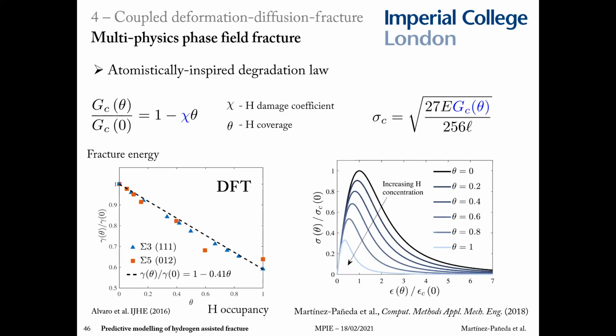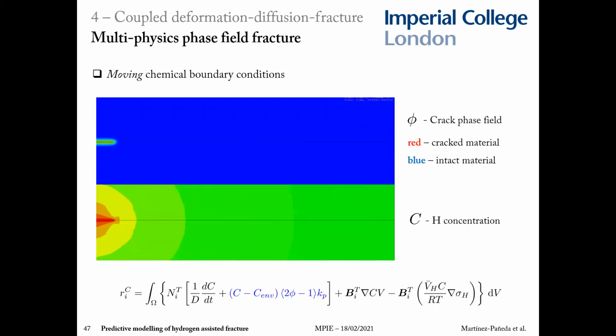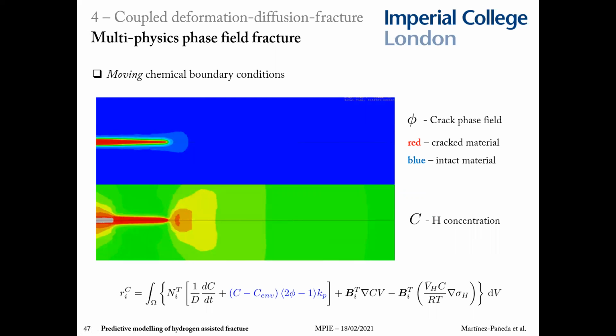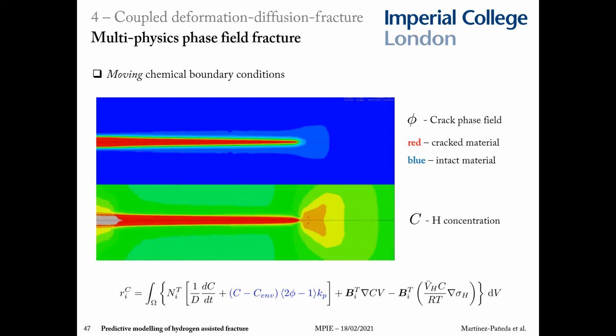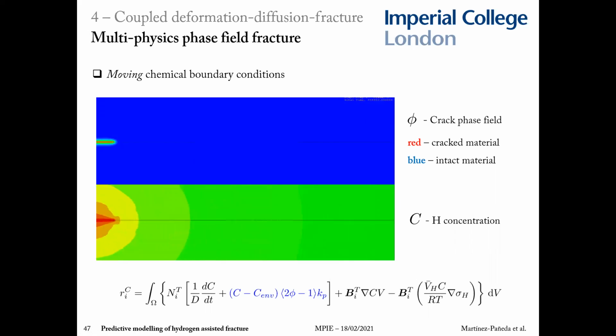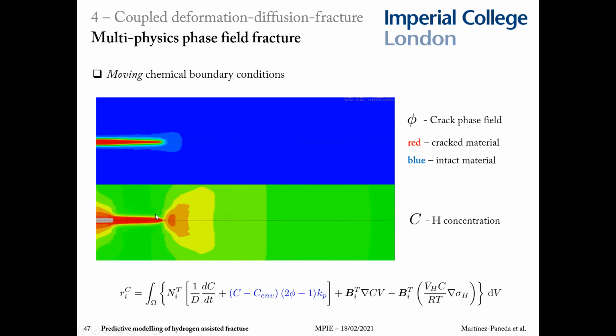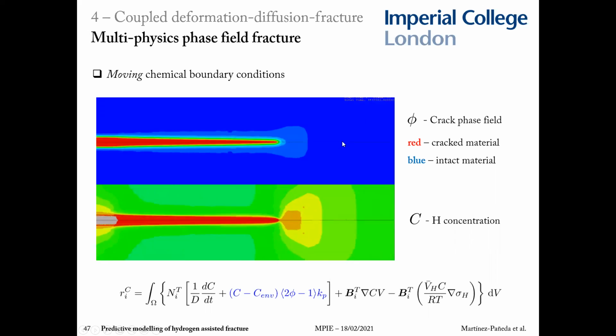So if you consider the role of the hydrogen, then what you can see is how the strength diminishes as you increase the hydrogen concentration. So that's what you get there. And one last comment on the coupling between the phase field and hydrogen. One thing that you should consider if you want to capture precisely the crack propagation stage is the fact that the environment, the hydrogen gas or the aqueous electrolyte, will probably occupy the newly created crack surface. So you need moving boundary conditions for the diffusion problem. You can see in this video that in the context of phase field fracture, one can use a penalty approach to readily capture how the hydrogen concentration of the environment follows the crack as the crack propagates.